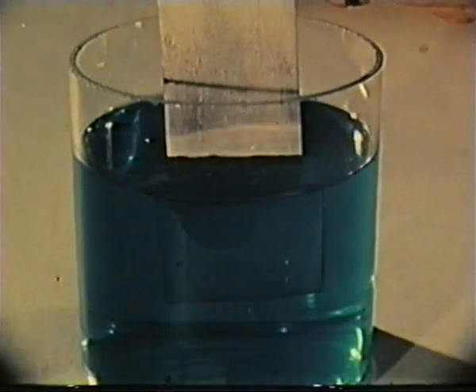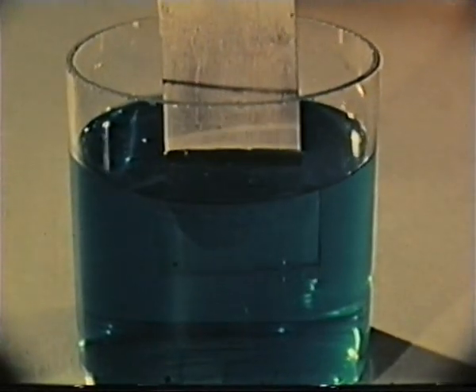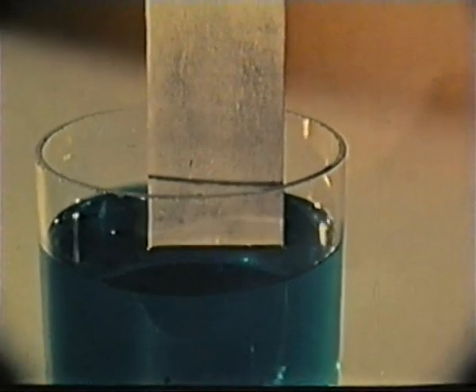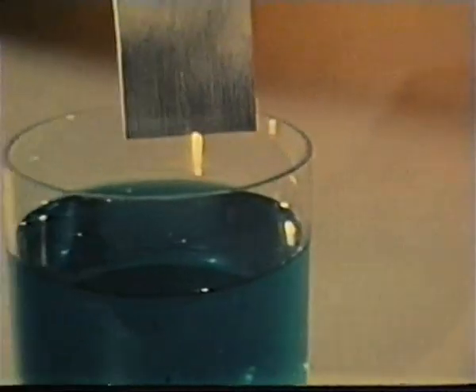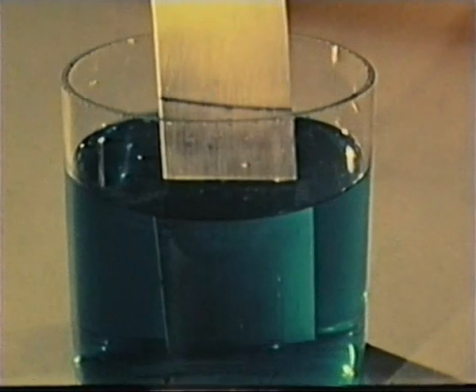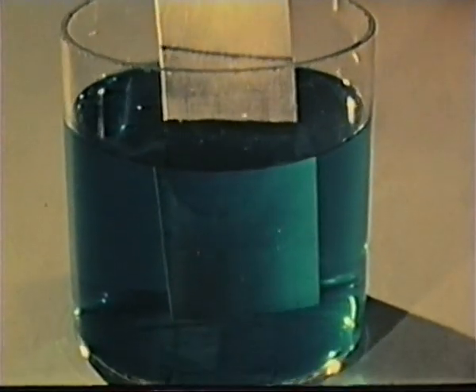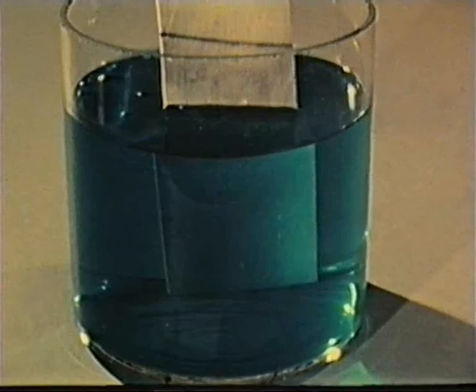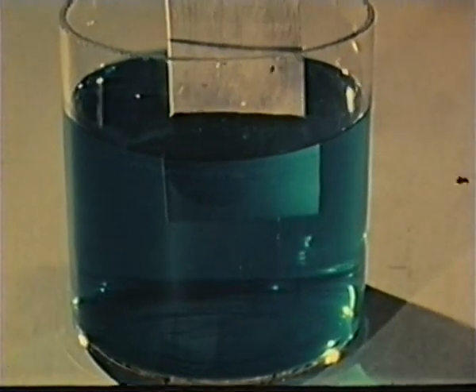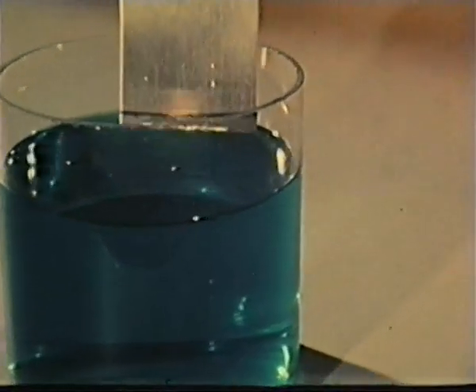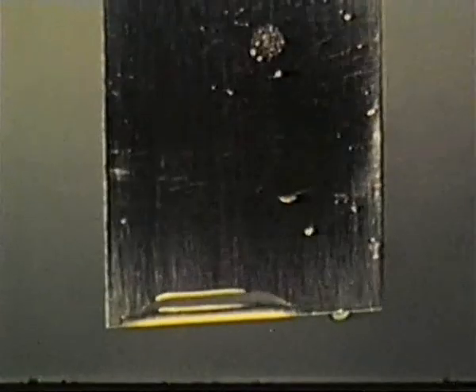When the alloy contains about 12% or more of chromium, it achieves substantial passivity and will resist corrosion in many environments. And of course, the 18% chromium, 8% nickel stainless steel is also passive in copper sulfate. The increased chromium content and the presence of nickel have greatly extended the number of environments where useful passivity exists. This type of alloy is also much more easily fabricated and welded than the non-nickel stainless steels. This passivity is substantial and cannot be destroyed by striking the specimen with a glass rod, such as occurred with the ordinary steel specimen treated in this way.